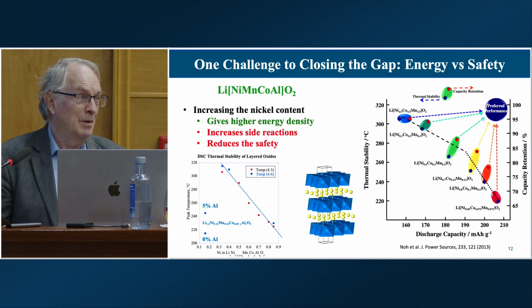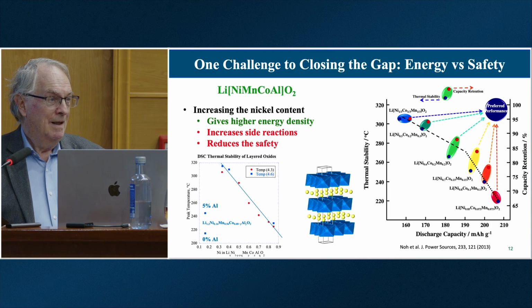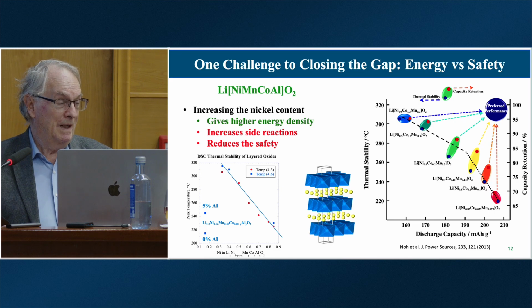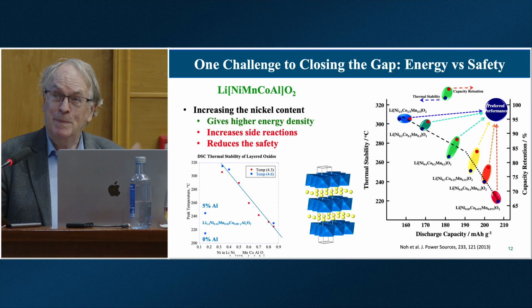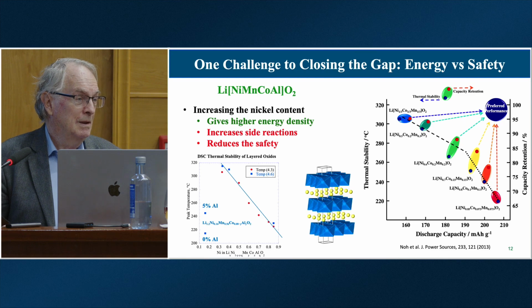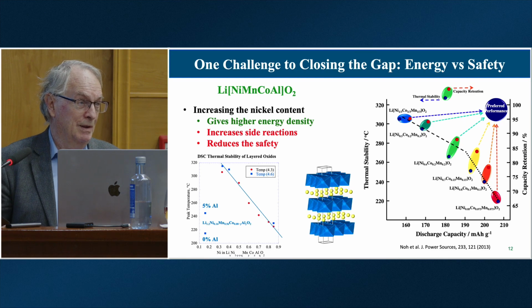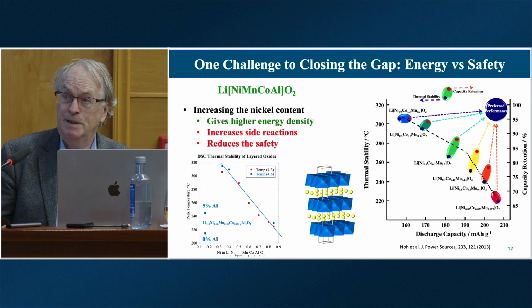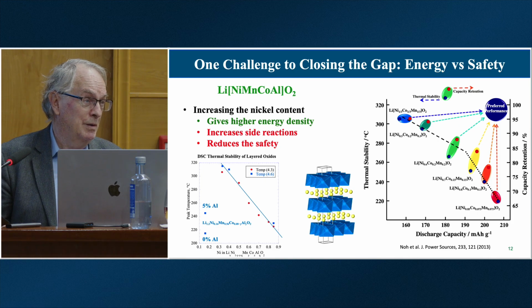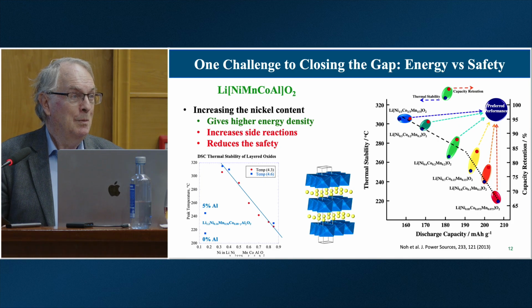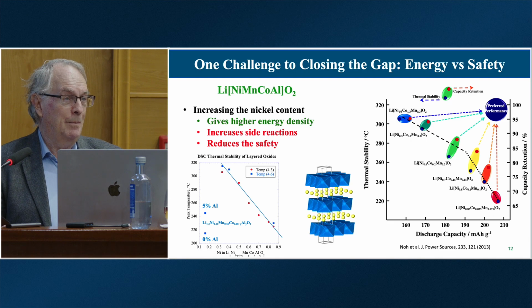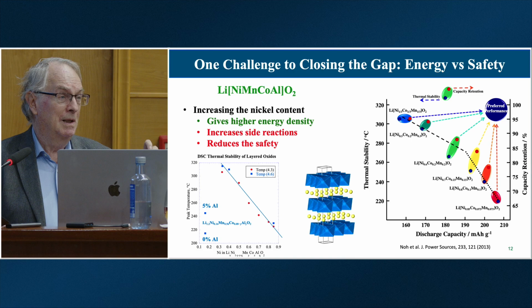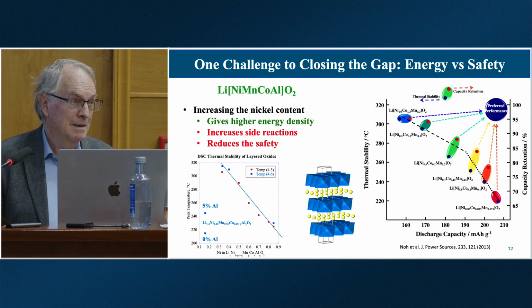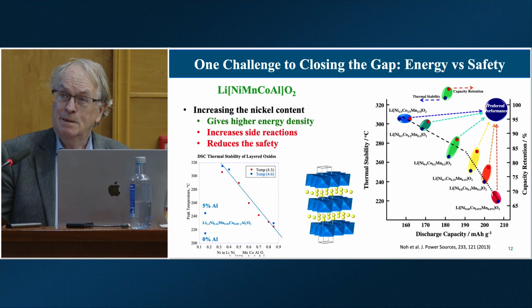As I mentioned, talking about lithium cobalt oxide, these are not stable materials, they're metastable. None of these metals likes to be 4+. So if you heat them up, they will lose oxygen. So you can see the highest nickel one there will lose oxygen at 220 degrees centigrade. We're never going to take the batteries to those temperatures, but that's a direct measure of how reactive these materials are with the organic solvents. So the lower the thermal stability, the more reactive they are.